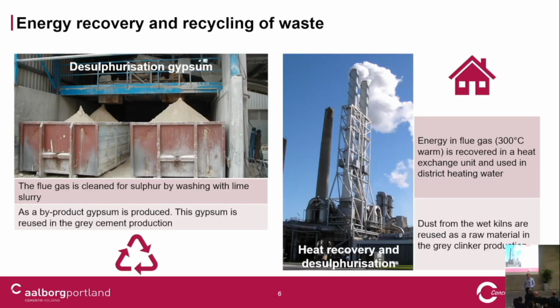And that's bad, but we have learned, Michael told us this morning, that we have a heat recovery system at our plant, so we actually recover 25% of the energy put into the kiln. So even though we have these wet kilns, our total energy balance, you can say, is not that bad. And our EPD is not that bad for the cement.